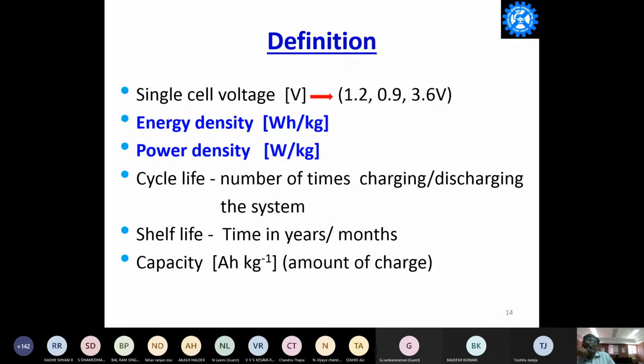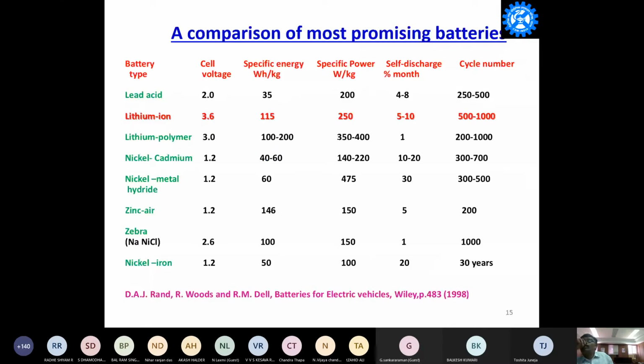Now I am coming to the energy density and power density. You can use lithium ion batteries for your laptop computers and mobile phones, but they cannot be used to start your vehicle or for UPS at present. Similarly, lead acid batteries, which are used to start your vehicle and for UPS, cannot be used for laptops. You can use them, but the weight of the laptop is maybe 0.5 or 1 kg, whereas the lead acid battery weighs around 10 or 15 kg. So the energy density of a lithium battery is very high compared to a lead acid battery, whereas the power density of a lead acid battery is very high compared to a lithium ion battery. This is the difference between energy density and power density. If you compare cell voltage, specific capacity, power density, self discharge, and cycle number, the lithium ion batteries stand first.